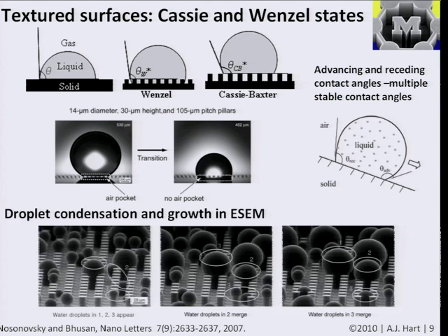And there are ways also, for example, to observe the migration and wetting of surfaces at relatively small scales. And this is a picture of a study of the wetting behavior of a surface inside an environmental SEM, where they're condensing water droplets on the surface while watching it happen. So this is happening at low pressure, and you're just letting a little bit of water vapor into the chamber, and the droplets are condensing.